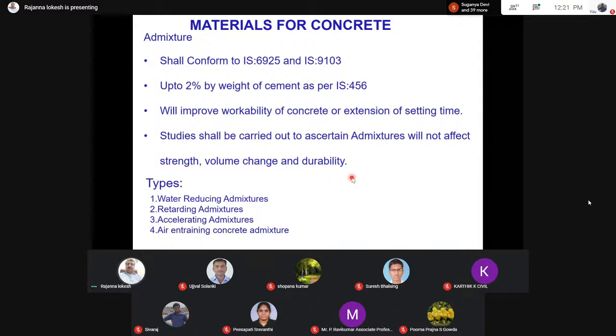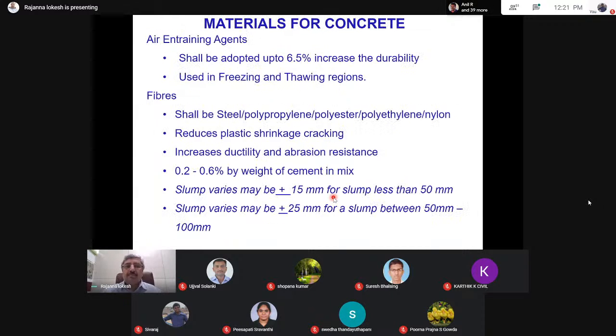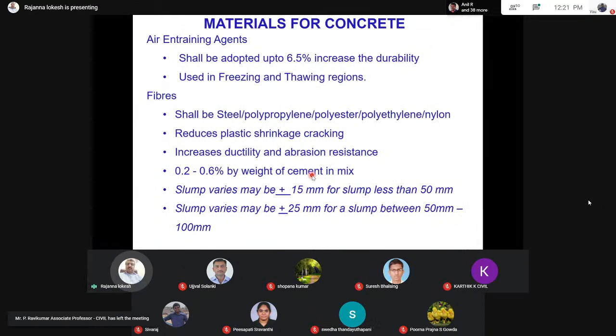Studies shall be carried out to ascertain the compatibility of admixture and the durability and the strength. The type of admixture can be water reducing admixtures, retarding admixtures, accelerating admixtures, and air entrainment admixtures. When we are working in a very cold temperature zone, it is important for us to go with an air entrainment agent of around 6.5% to increase the durability.